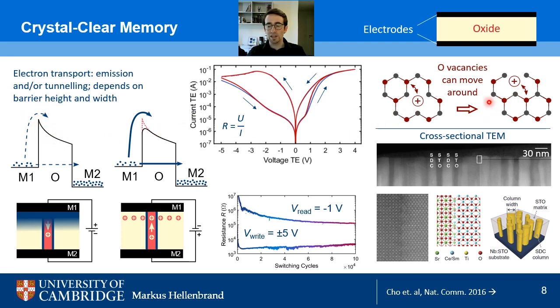So then we can tie these two together. By accumulating oxygen vacancies, we lower the height of the barrier, which means more electrons can get over it. And by depleting oxygen vacancies from the interface, we increase the height of the barrier so that fewer electrons can get to the other side. And this is now how we relate the configuration of the oxygen vacancies to electronic conduction, and thus to a readable state of information in a computer. So we can say now that if we have a larger current, so more electrons getting over the barrier, this is our state number 1. And if we get fewer electrons over the barrier, this is our state 0. And again, here we have the binary alphabet that we need for a computer to store information.